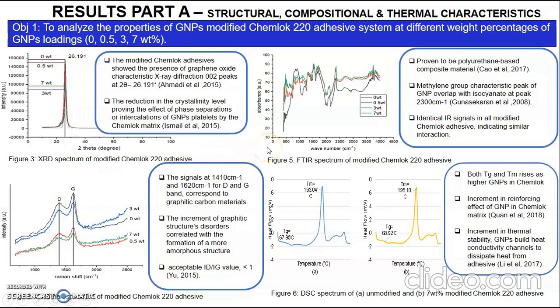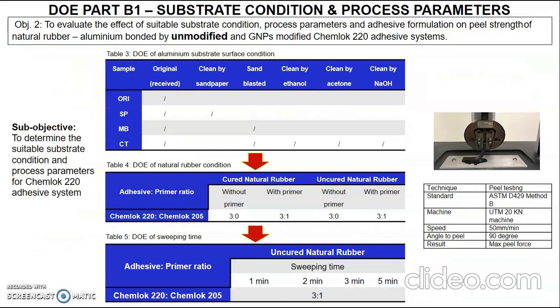From the compositional analysis, it can be seen that the Chemlok has characteristic peaks like a polyurethane-based composite. The methylene characteristic peak of GNP overlaps with the isocyanate group at peak 2300 per centimeter wave number. And last but not least, the thermal analysis. Both Tg and Tm increase as the GNP increases. This proves that GNP plays a good role to build a path for heat dissipation.